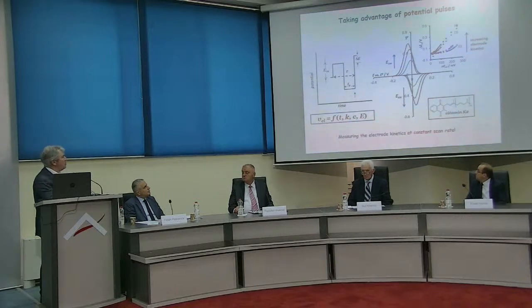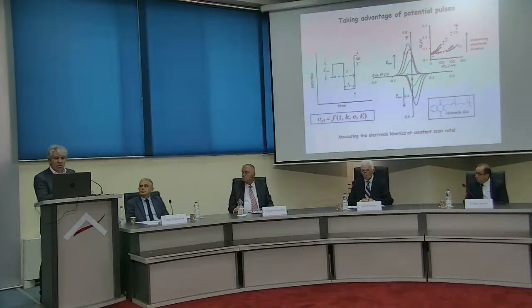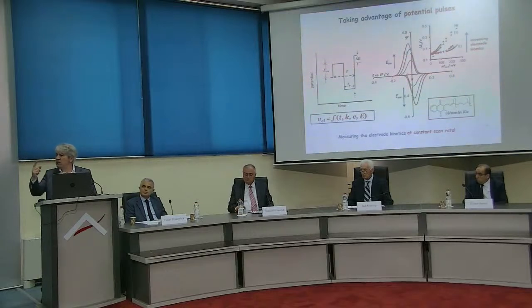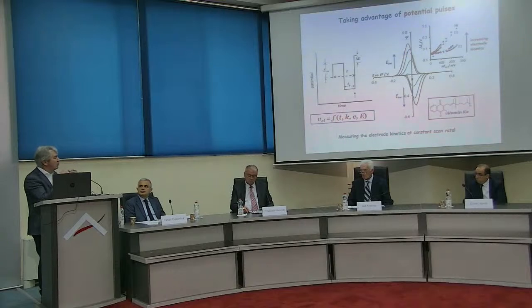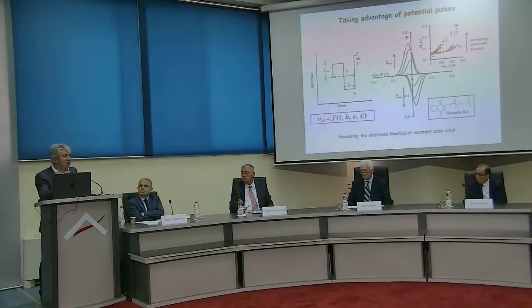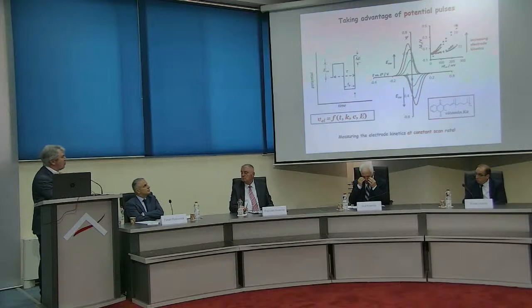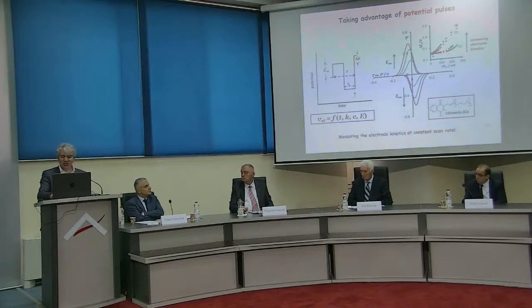And then I can do something which is not possible with other techniques. For instance, electrochemists know that if they would like to measure the rate of the reaction, which is critically important for batteries, then we must study the system by scan rate analysis, because scan rate analysis means simply I change the time of the electrochemical experiment. I must change the time if I would like to measure the kinetics, like in chemistry generally. Here, that is possible at a constant scan rate, simply using the intensity of these pulses. And that was a very, very strange claim from us in a publication together with my colleague Kirill Lysichkov, in which we claim that we measure the electrode kinetics at a constant scan rate. And that was really a nice contribution.